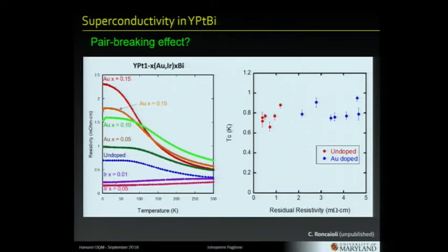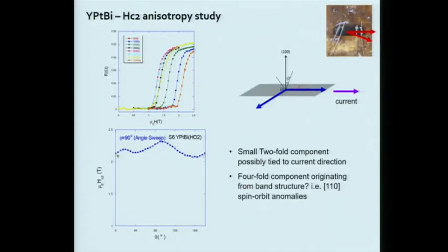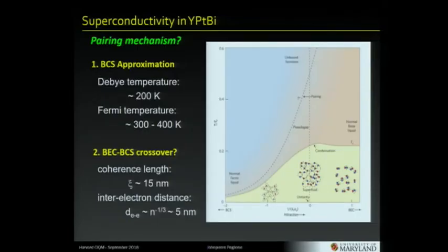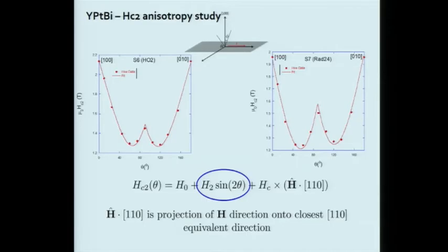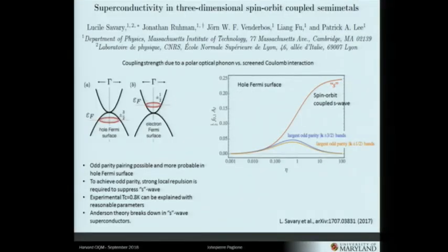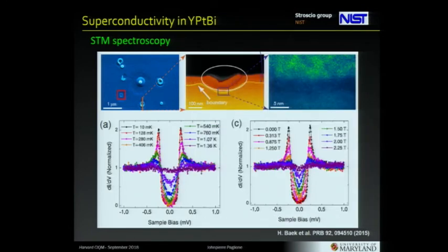Have you actually looked at the vortices in this material? I think that since the penetration depth is so long, you probably want to use scanning SQUID or something. So is that something you're pursuing? Because the shape of the vortices should tell you more about where the nodes are. Right. So the best we've done was this work with Joe Strozio. So we're not doing that ourselves, but we tried some STM work a while back. I've probably showed you this.